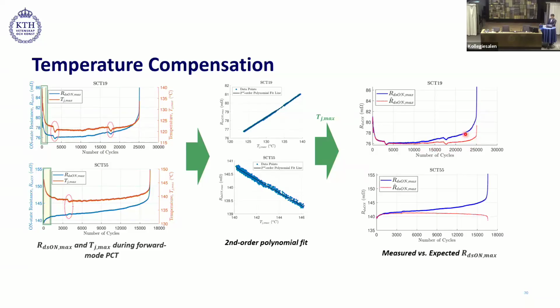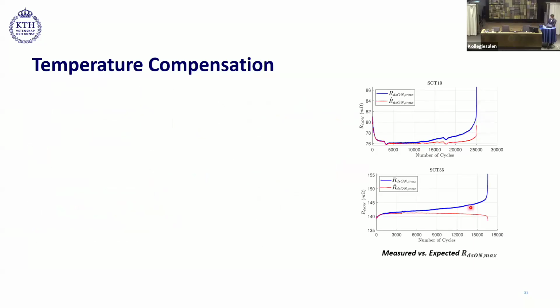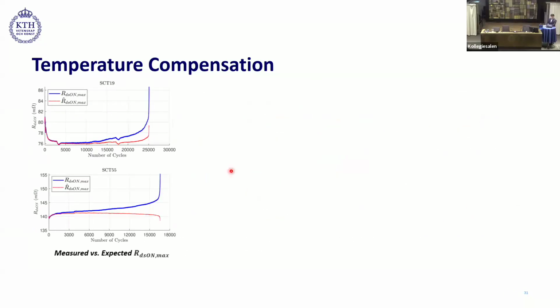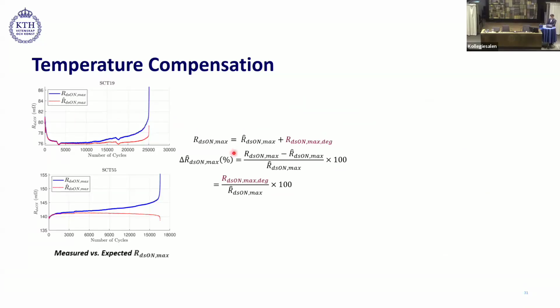The blue curve represents the measured value of RDS on max. And we see that the 2 curves diverge from each other, and the rate of divergence increases towards the end of life. Similar observations were also made in SCT55 device. Then we used the RDS on max and R hat DS on max, which is the expected value, in the temperature compensation model, which is represented by these equations.